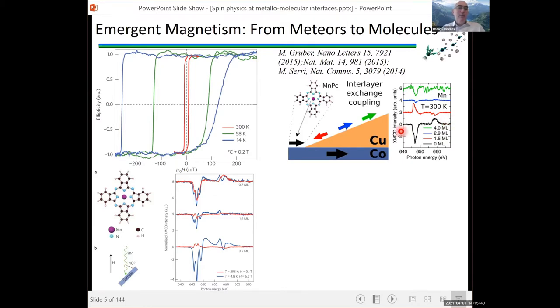But depending on the separation introduced by the copper spacer between the cobalt and the manganese, you could have either ferromagnetic or antiferromagnetic coupling. So not RKKY, but a similar effect in that you can alternate the ferromagnetic or antiferromagnetic coupling, obviously weakening as you separate both layers, but inducing that different magnetization in the molecule.